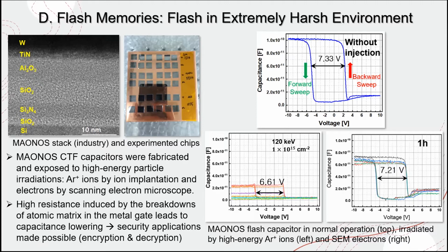The high energy particles were ions, argon ions, and electrons, which can be easily found in the ion implanter in the fabrication facility, and the high energy electrons can be found in the SEM microscope. After injection of high energy particles for a certain amount of time at a certain amount of energy, what can be commonly observed is the reduction of the maximum capacitance, and the memory window is reduced too. So the final result could be derived as the gate was permanently broken down.